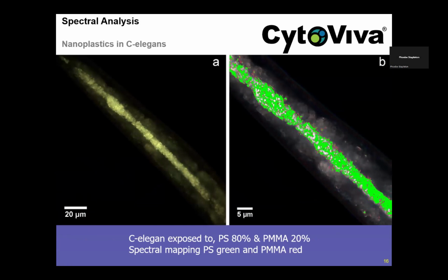And in this last image of this example research that I'm going to show very briefly, C. elegans were exposed to two different polymers, 80% polystyrene and then 20% of the PMMA sample. And then using the spectral response measurements of these two different polymer samples, mapping of the two was conducted inside the C. elegans. And you see here that most of the spectral mapping that occurs is green, which is consistent with the polystyrene. And then you see some areas of red that map, which are consistent with the PMMA polymer. And this spectral mapping and the class distribution from this spectral mapping matched almost identically the percentage of exposure that the C. elegans was exposed to, demonstrating the accuracy of the instrument to discern between the two different polymers that had been ingested by the C. elegans in this case. So a really interesting example.